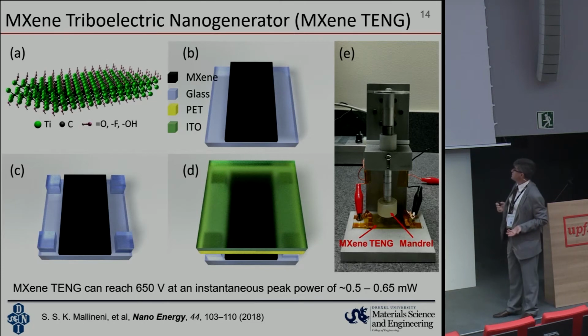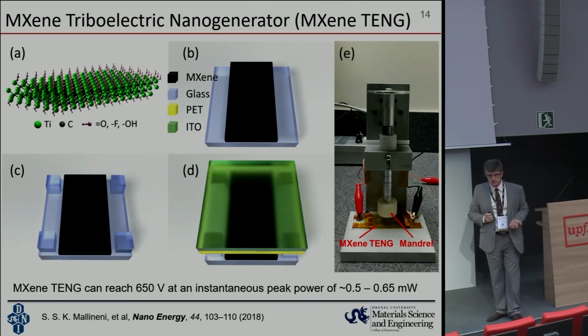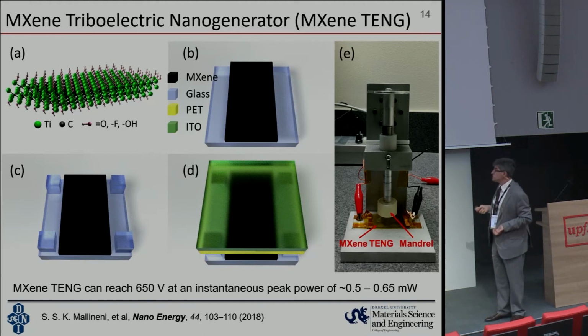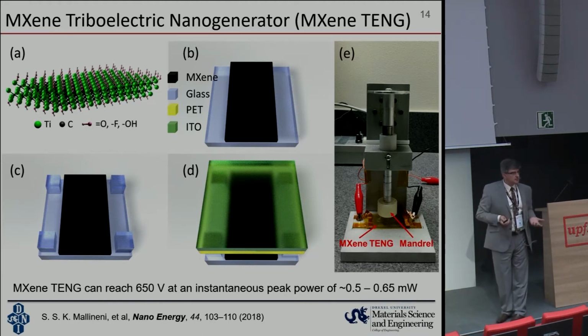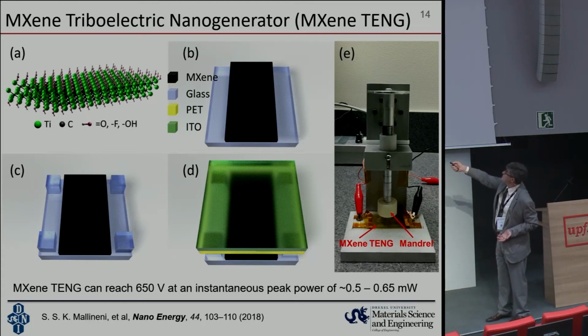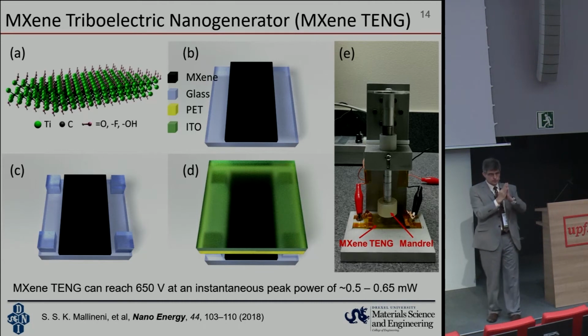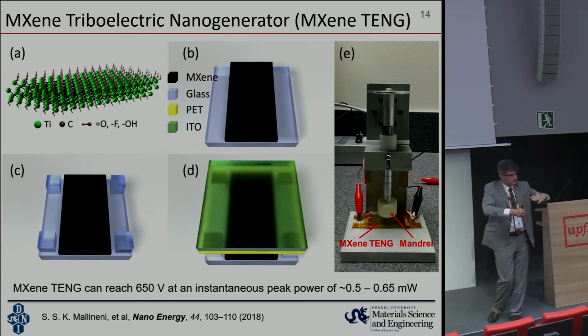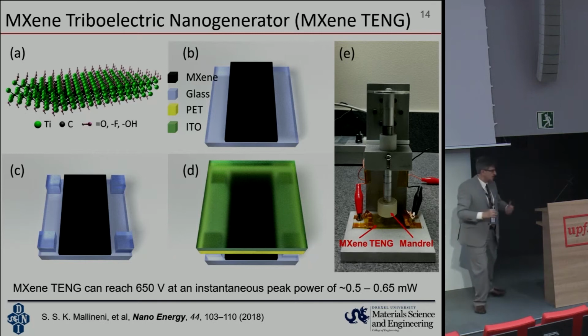So it's very easy to produce, and we worked with colleagues from Clemson University on demonstrating that actually MXenes can be used in a Triboelectric Nanogenerator, depositing a film of MXene on glass, testing it against PET, ITO films here, and basically using this mandrel, just pushing and showing. And actually in triboelectricity, you can do a variety of different motions. It can be a sliding motion between the layers. It can be simply compression. As long as you bring 2 surfaces in contact with different work function, when electrons can tunnel from one surface to another, you can collect charges here.